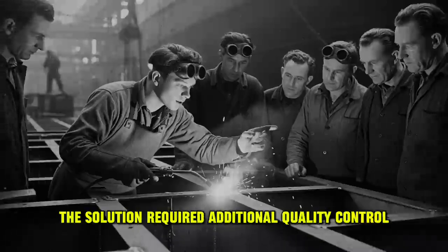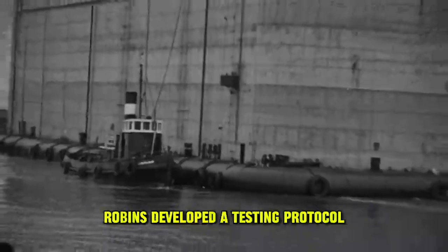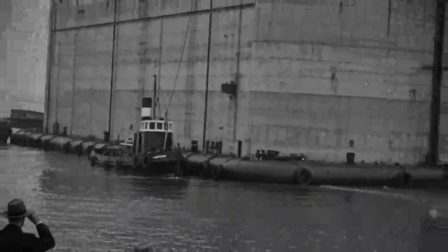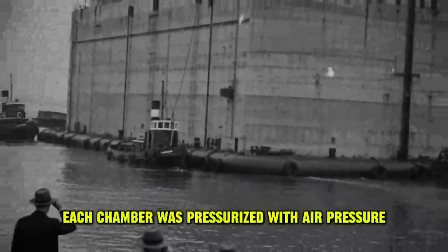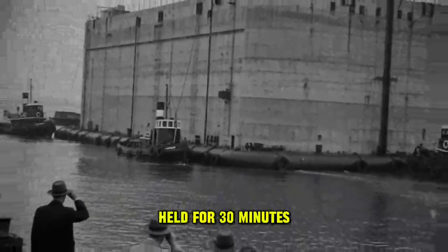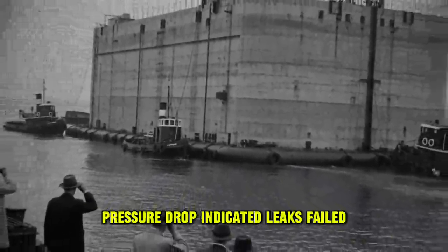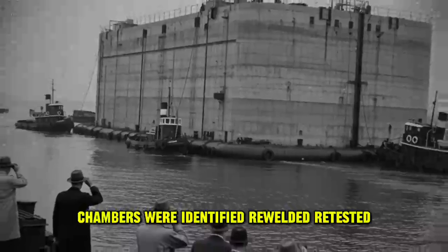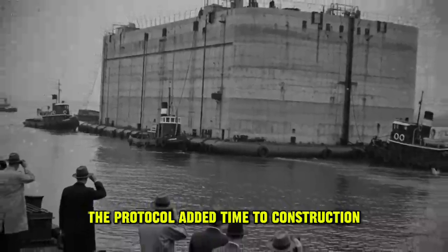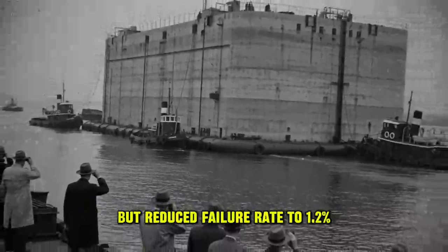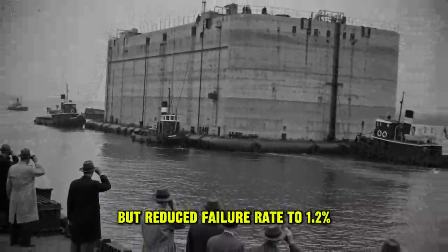The solution required additional quality control. Robbins developed a testing protocol. Each chamber was pressurized with air. Pressure held for 30 minutes. Pressure drop indicated leaks. Failed chambers were identified, re-welded, retested. The protocol added time to construction but reduced failure rate to 1.2%.